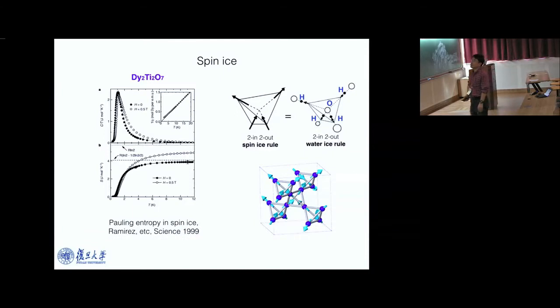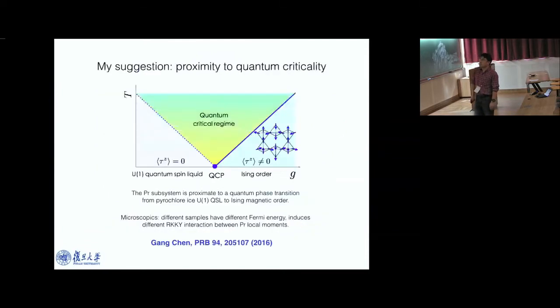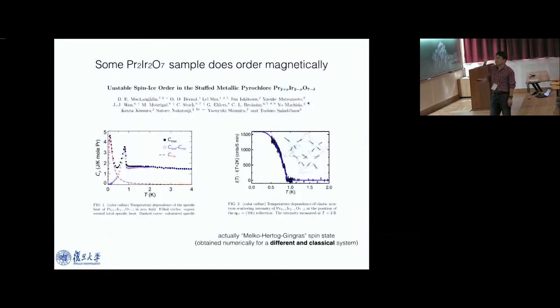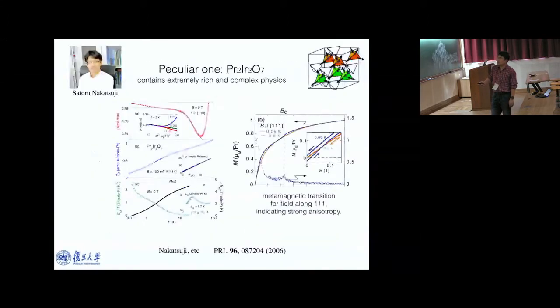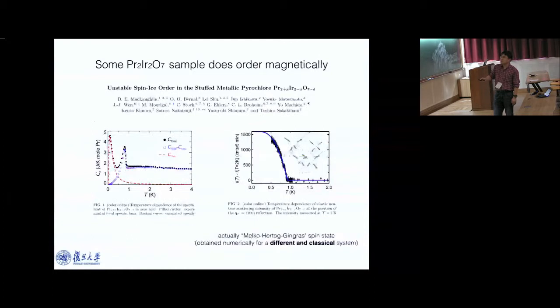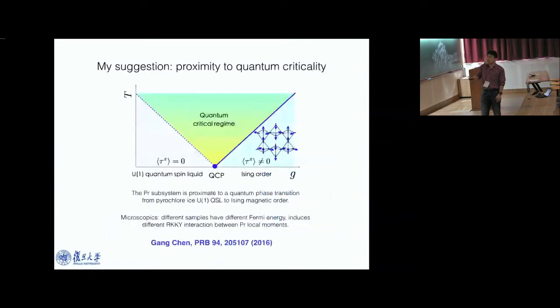So this is the classical spin ice where the spin is treated classically. The suggestion for this system is as follows: the system sometimes remains ordered, sometimes becomes disordered. The local moment is, most of the time, disordered, and sometimes becomes ordered, from the neutron scattering measurement. So that means the local moment system is proximate to a quantum phase transition from some kind of disordered state where the spins are strongly fluctuating to an ordered state. So what's the nature of this disordered state?